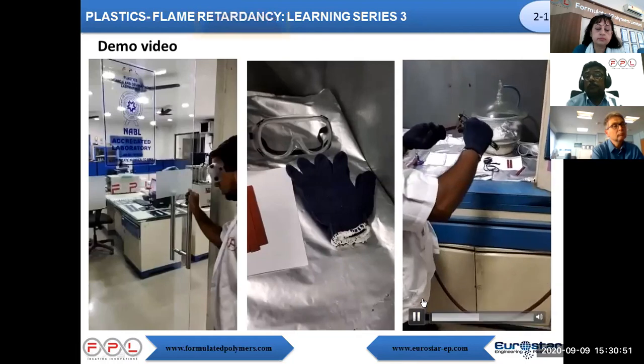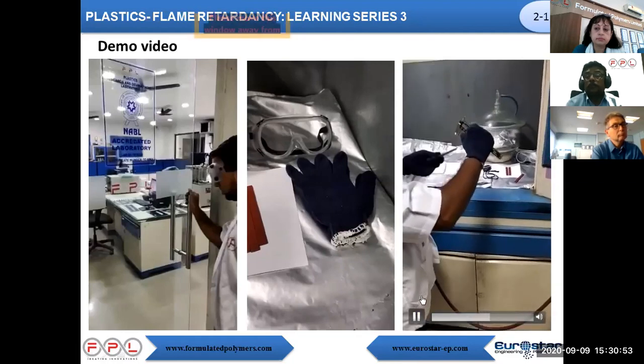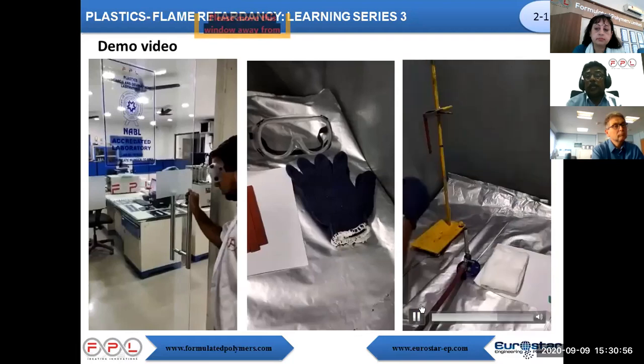And in the next part, equipment setup. Specimen length, width and thickness need to be measured and recorded. Then it should be positioned in the fixture at a vertical angle. Then the cotton bed underneath should be at 300 mm length. Then the flame height should be fixed exactly at 20 mm by adjusting the gas flow rate.